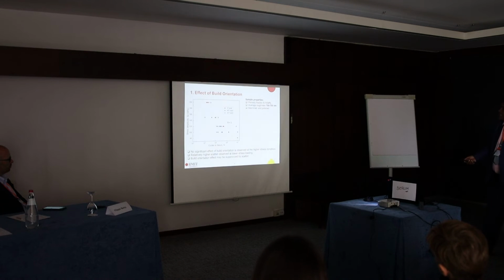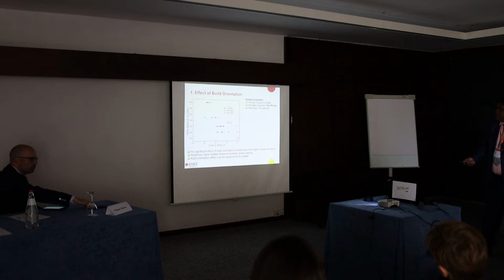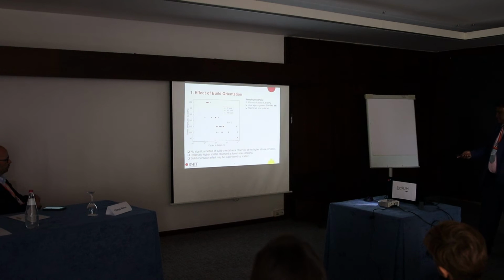These are the details of the different machines we have used, in case you want to repeat this kind of test. But then we are going to present these 4 effects. The effect of build orientation is very important. We found there is a high scatter and no significant effect of build orientation at a high stress condition.